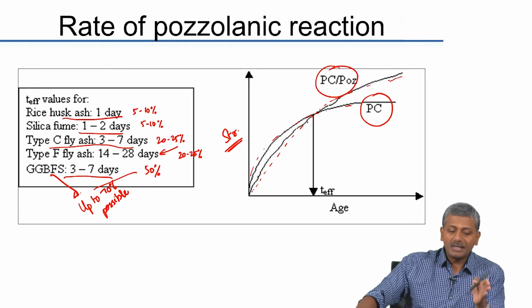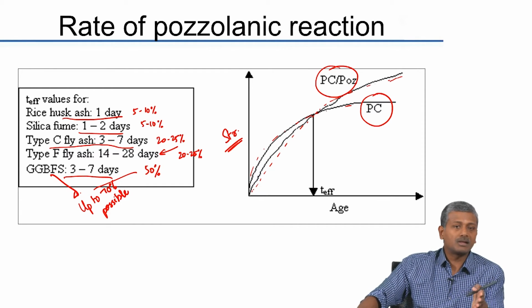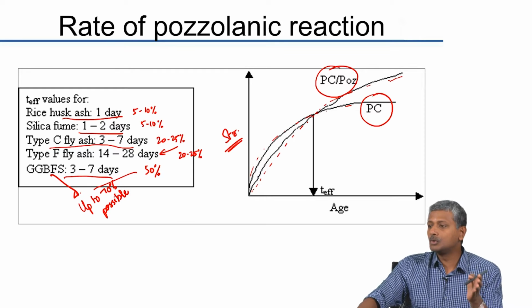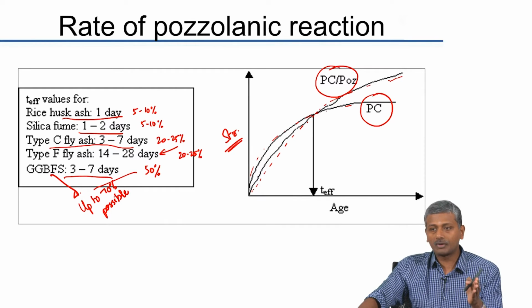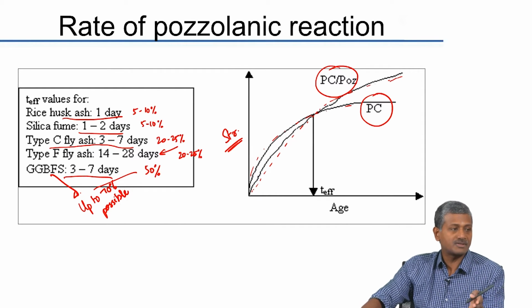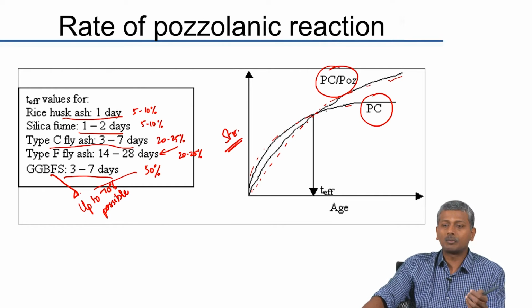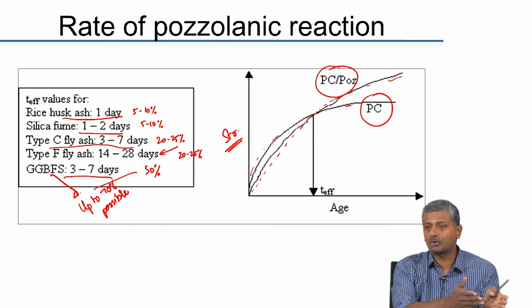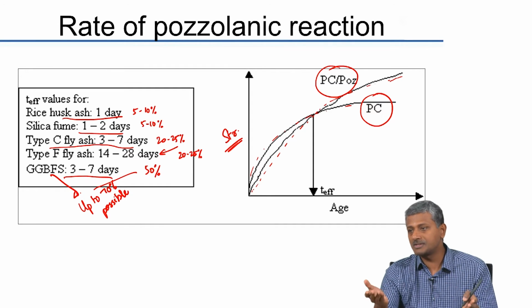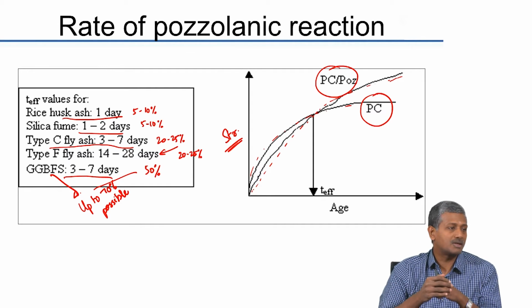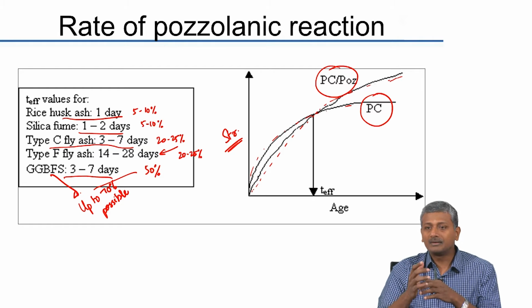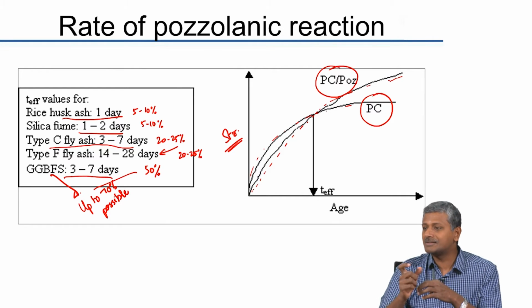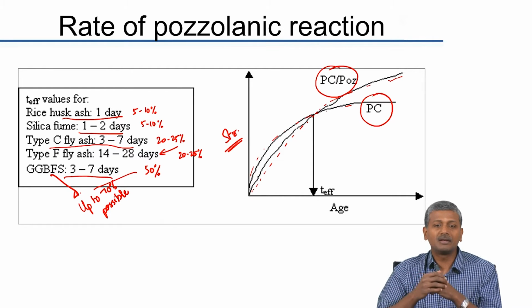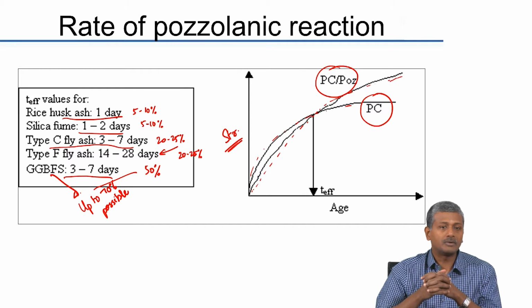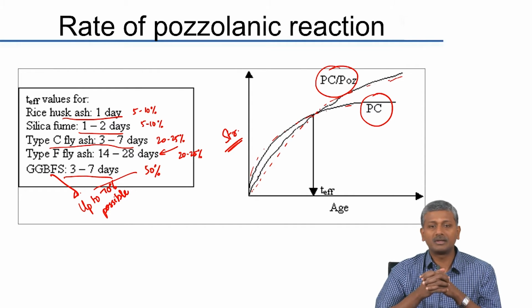Okay. So, these are assuming that you are replacing these materials at their conventional rates and that you do adequate amount of curing. Okay. For example, if you do not cure type F fly ash based systems for that duration of 14 to 28 days, it may never reach the strength of your Portland cement mixture. So, if you do the same level of curing for fly ash based systems as you do for cement systems, you may not get adequate strength development. So, that is one thing that has sort of acted against the use of blended cements in a more widespread fashion in the industry.